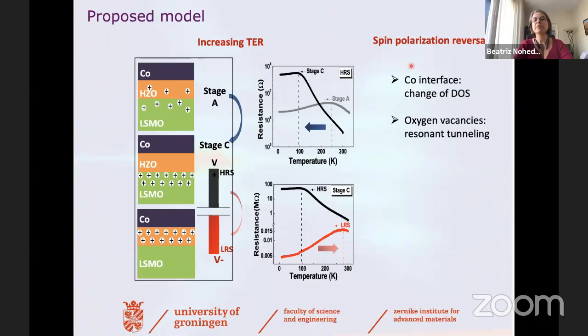this also can explain the spin polarization reversal, because we know that this can have two origins. First of all, a change at the cobalt interface, which can also be due to these oxygen vacancies in the hafnia layer that also change the cobalt, but also one can have resonant tunneling through oxygen vacancies, which is also consistent with this model. By now we have a better picture that this is correct by microscopy, but the paper is not out yet, so I will not say a lot more about this.